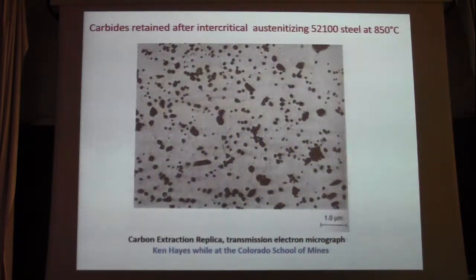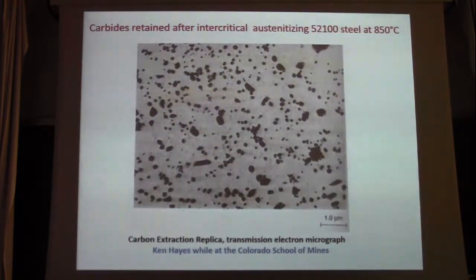Very fine carbide particles are produced, and basically what that does is remove carbon from the austenite. So the carbon now is in these carbide particles, and there's too small an amount of carbon to cause precipitation on the austenite grain boundary. So you can avoid the intergranular fracture by heating in the austenite plus carbide phase field, where you reduce the carbon in the austenite.